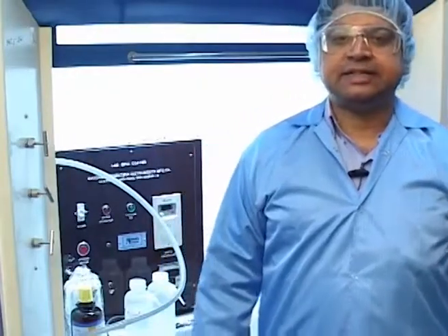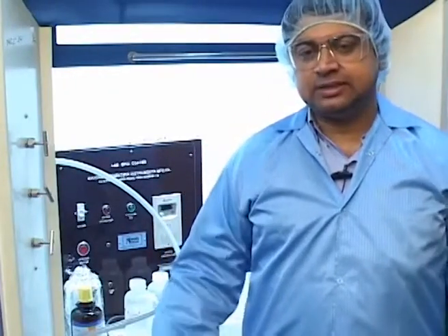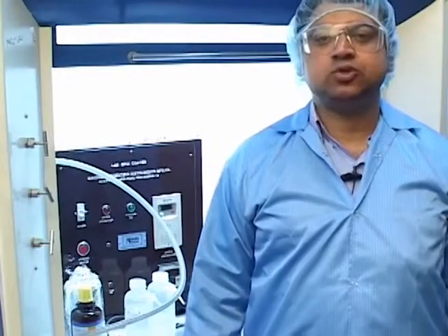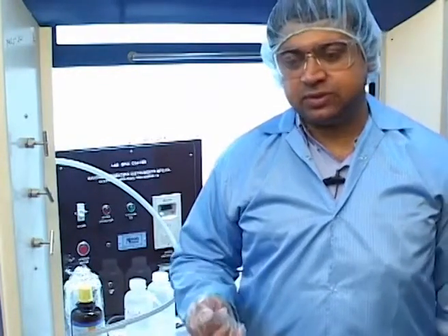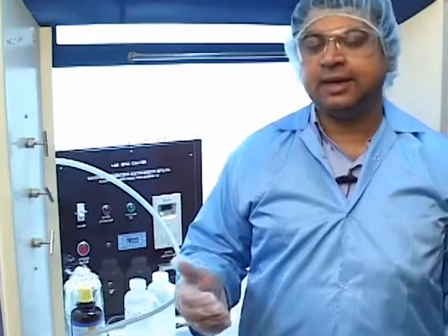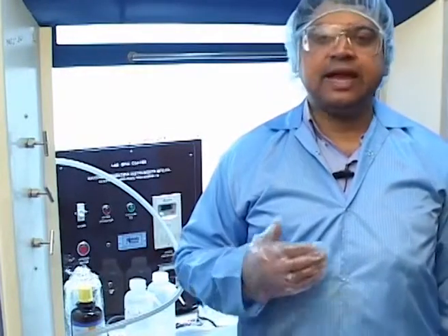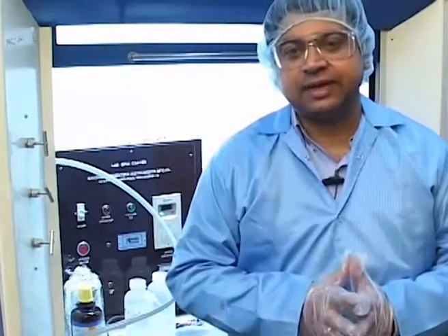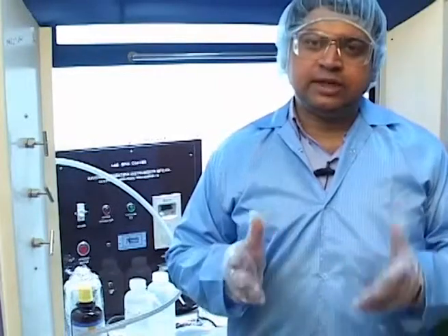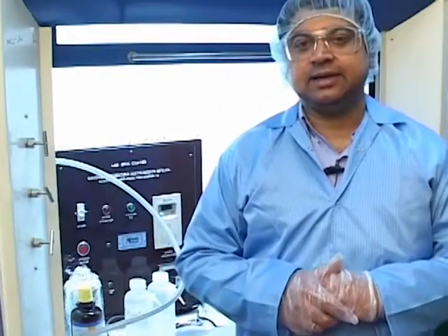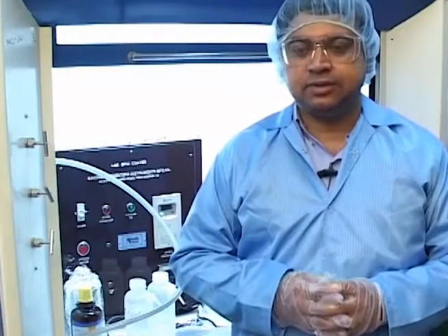So the next step basically is the clean wafer. Although it is very, very clean, we still need to do a surface treatment of the wafer so that, number one, it can be made hydrophilic. Number two, whatever organic contamination is there on the top of the silicon wafer gets removed. So one of the methods of doing that is by using an acidic solution called Piranha, which is essentially a mix of H2SO4 or sulfuric acid and hydrogen peroxide.